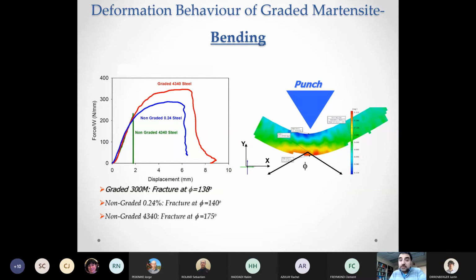We also tried bending, because there is an important benefit in terms of bending. If we have a decarburized material, the inside is very hard, but the outside is softer. So in terms of bending, most of the strain is on the outside. So one can imagine that this would be a perfect application for these materials with gradients. And in fact, it is.